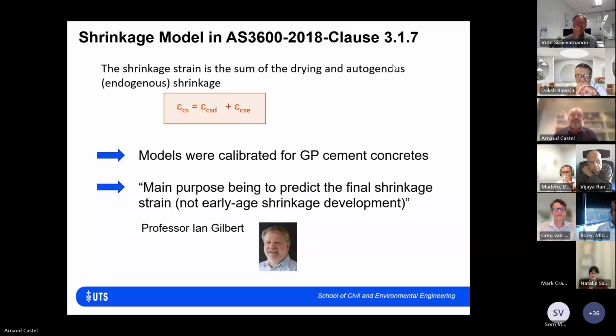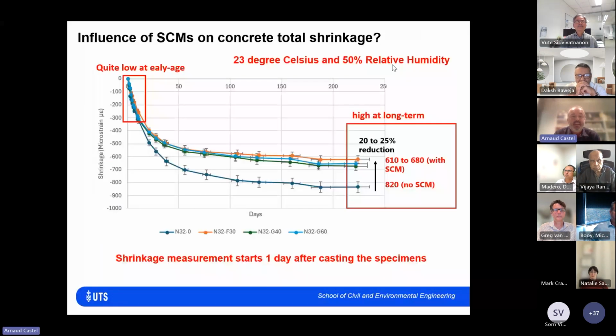One of the statements that Ian was always telling me is that the main purpose of those models is actually to predict the final shrinkage strain, not really what happens at early age. So don't be surprised if, when using the models, you're not getting a good correlation with the early age shrinkage, just because the models weren't calibrated and developed for early age. That's important, and it's again just showing that the models we have in the standards are not there for early age. They've been developed for long-term shrinkage. So that's a problem for what we are interested in today.